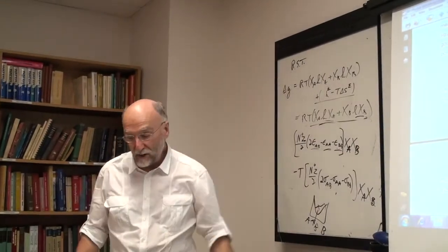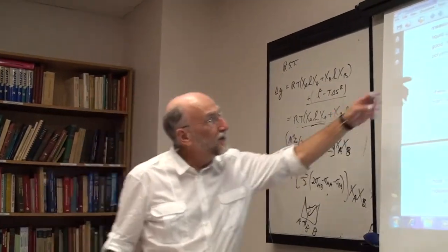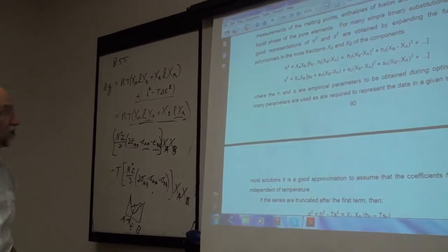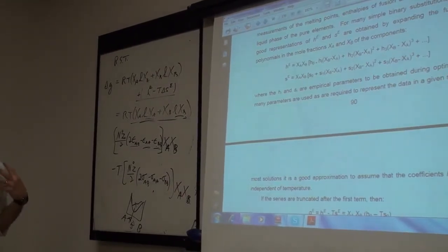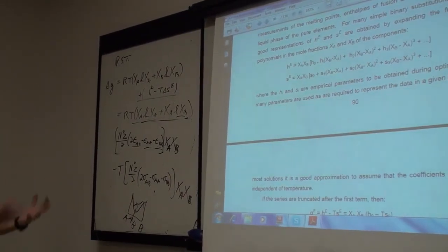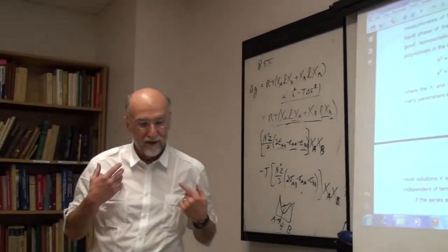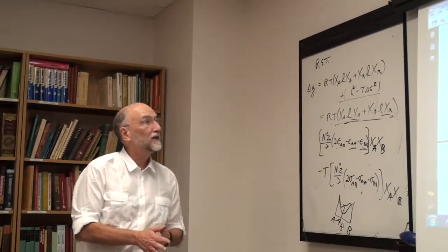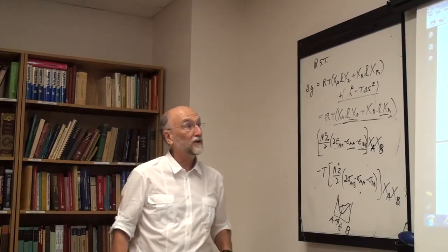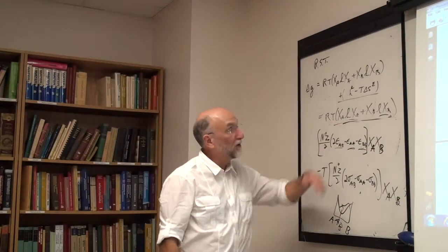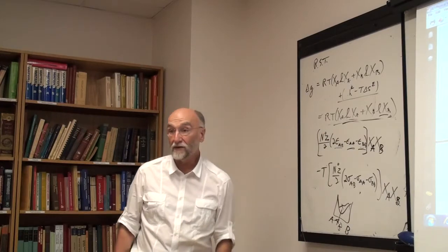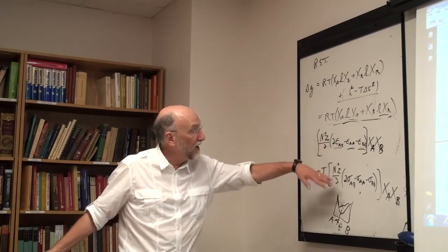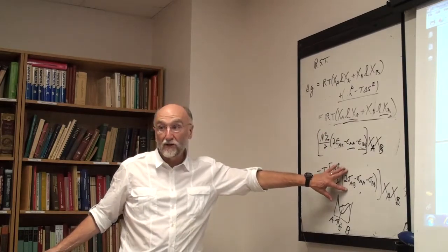So the polynomial expansion, of the excess heat and the excess entropy, is based on the same chemical assumptions concerning the structure as regular solution theory, i.e., to a good approximation, the system is randomly mixed. Okay, and it's just the bond energies and bond entropies that change with composition.